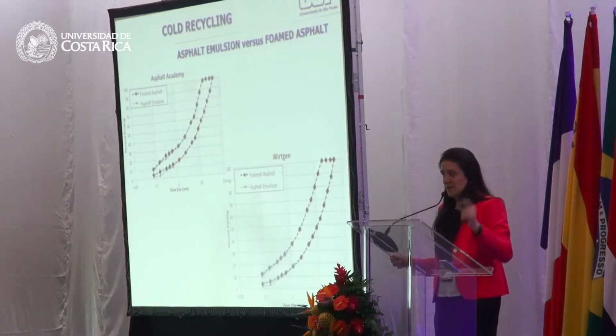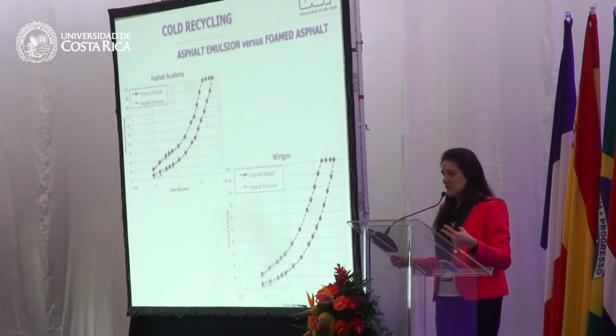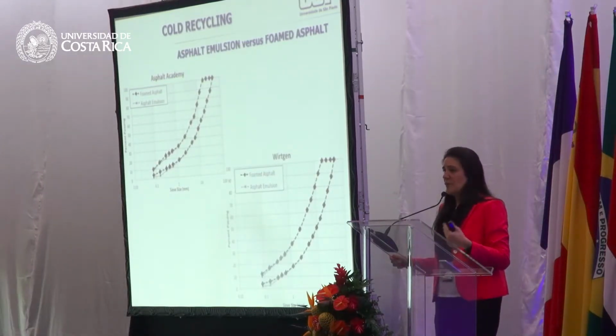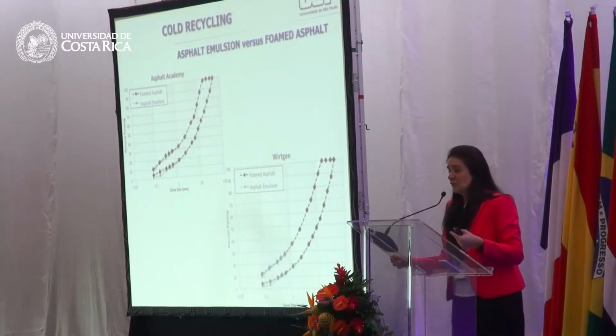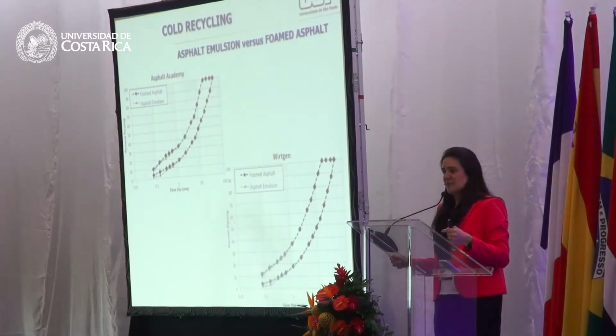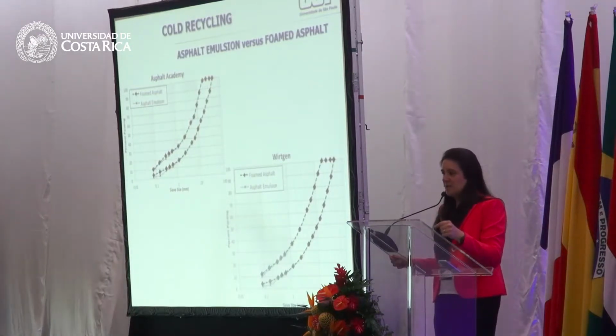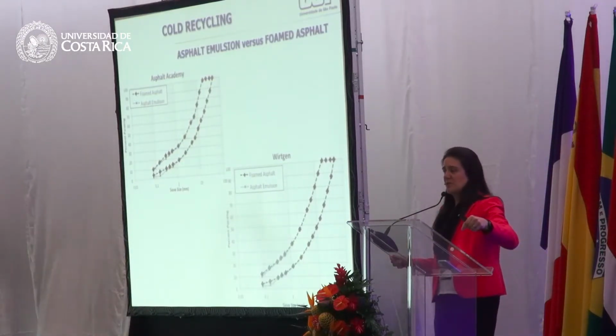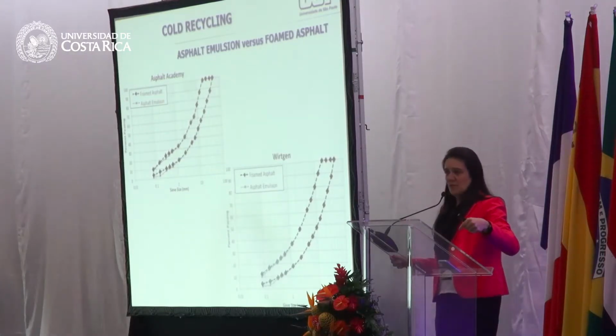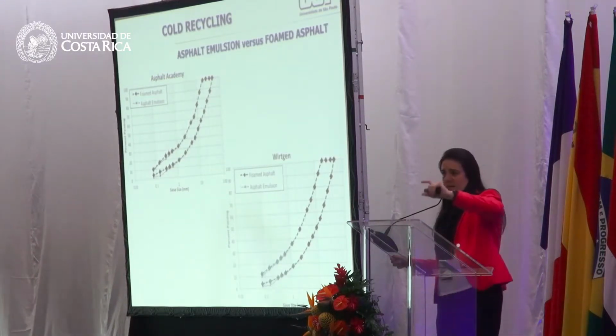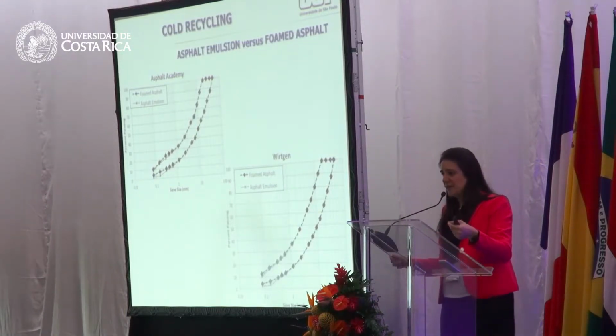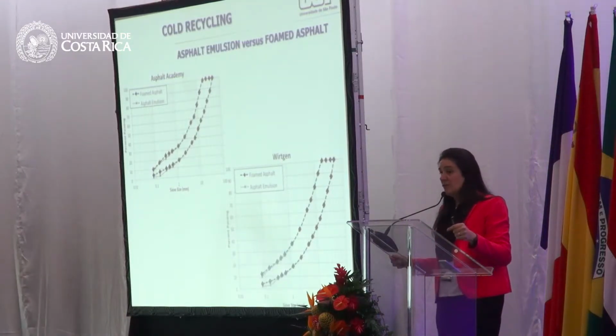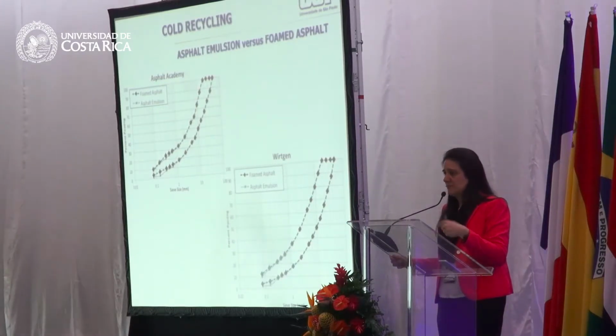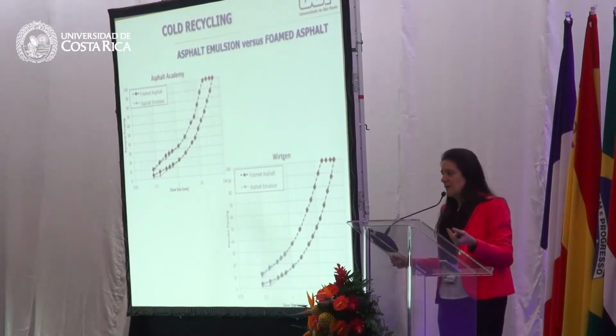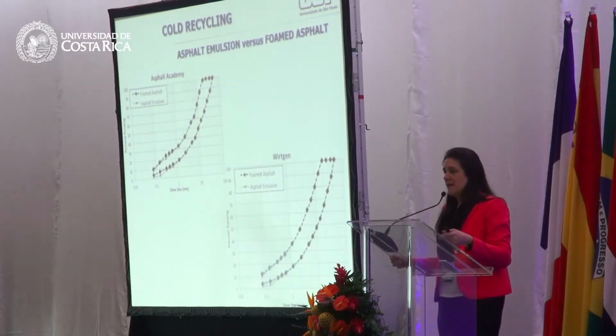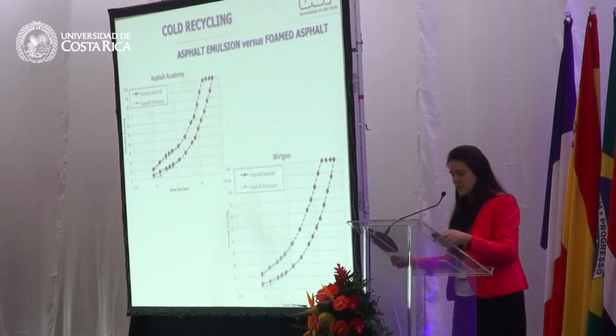If it's a new one and the bits are old, most probably the material will come up completely different. So the design of the mixture at a certain point will depend on the initiation of the process of RAP production. So if I have a RAP that is very coarse, without too many fines, eventually you have to add some new fine aggregates to compose this mix and make it fit into this gradation curve.